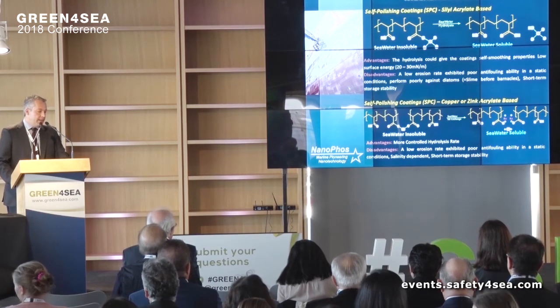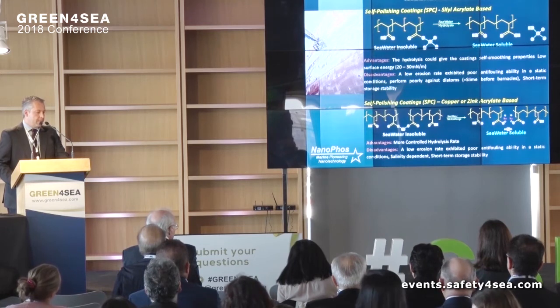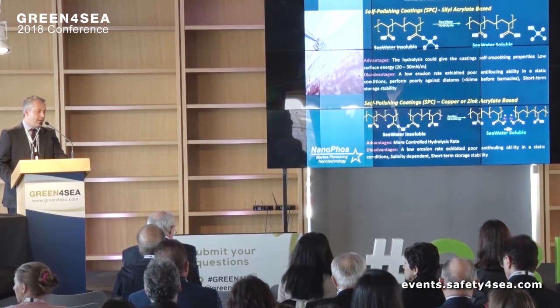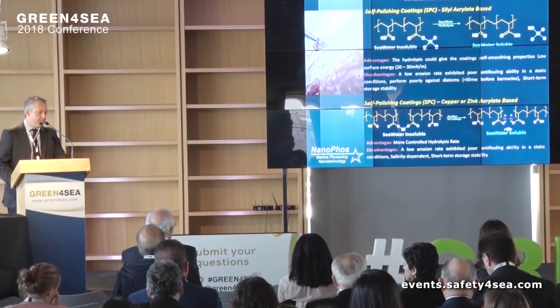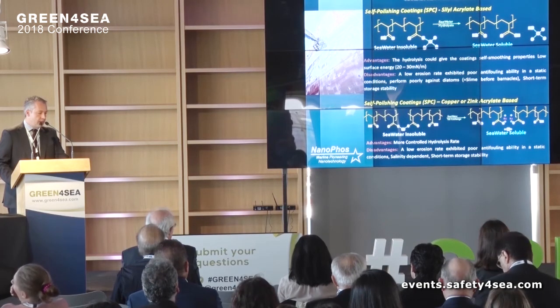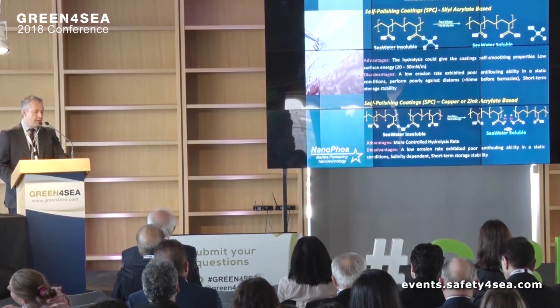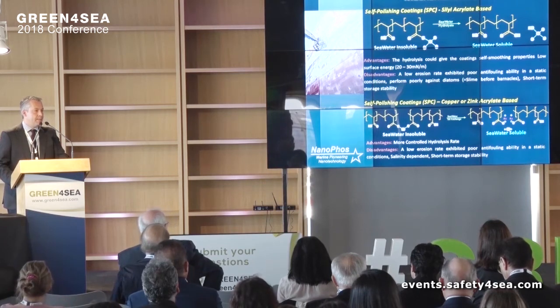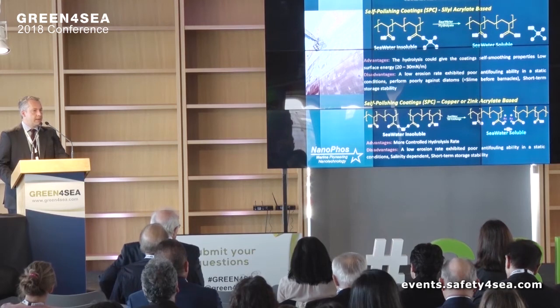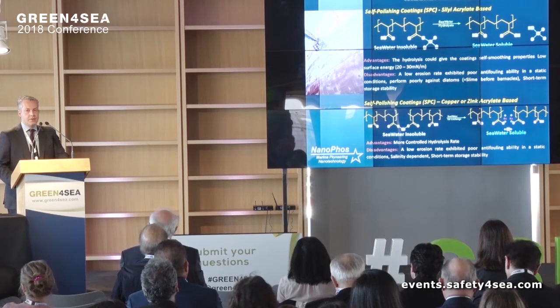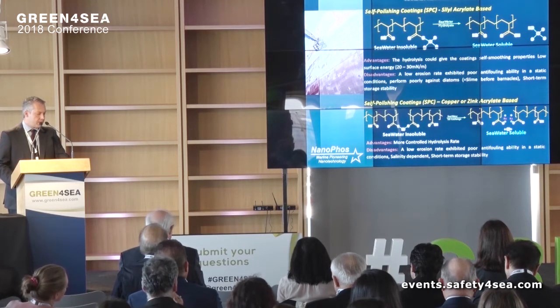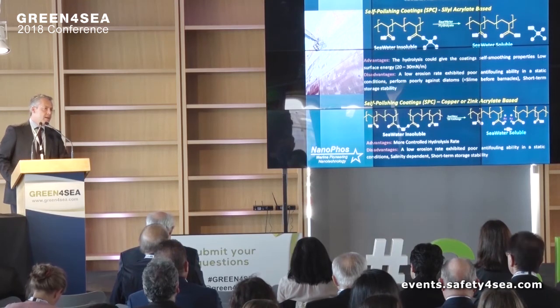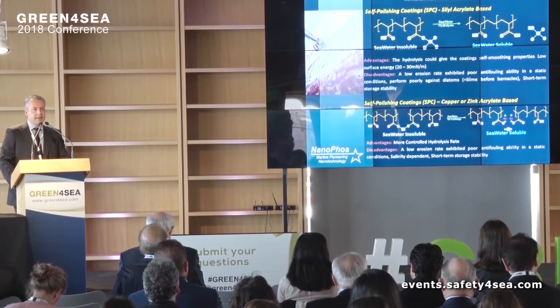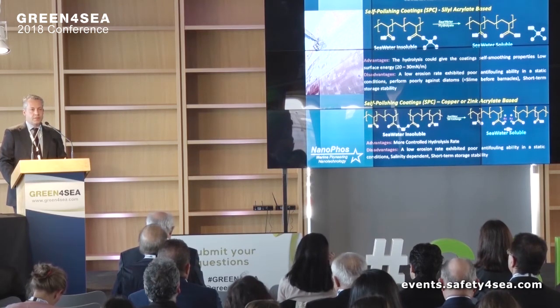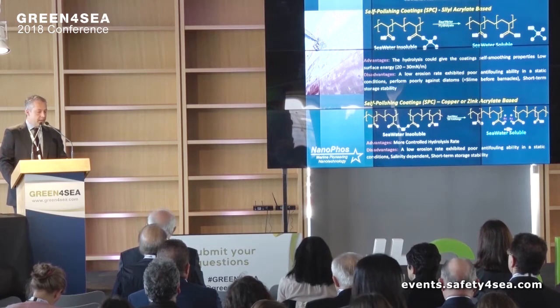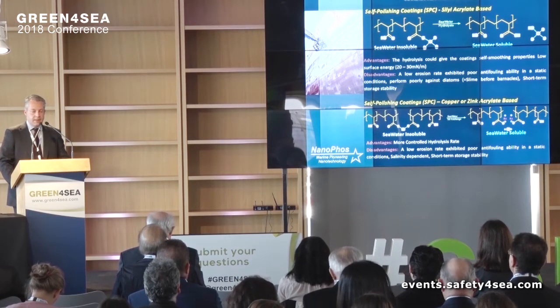The major difference between the silyl and the copper or zinc acrylates: silyl are based on some silicone molecules that hydrolyze, they break down. They present a lower erosion rate, but important is that they perform poorly, especially against the diatoms. It's the slime. So many silyl acrylate coatings carry slime along the bottom of the vessel. On the other hand, copper or zinc acrylate, they are a bit better, but again the problem is that they need ions, they need salt in order to get dissolved. So they do not perform very well, especially next to fresh water areas.